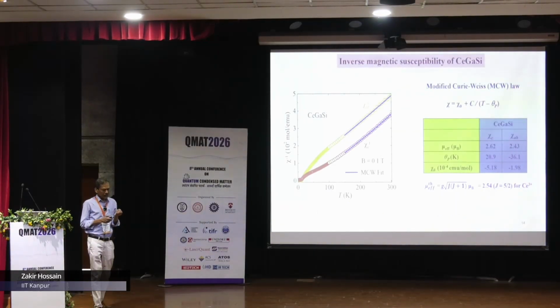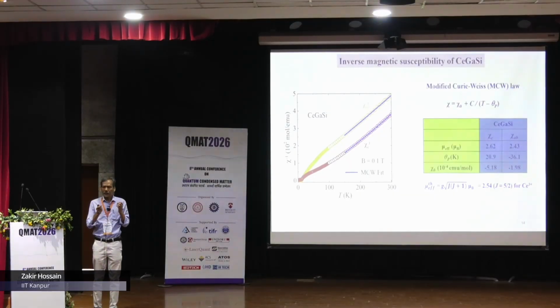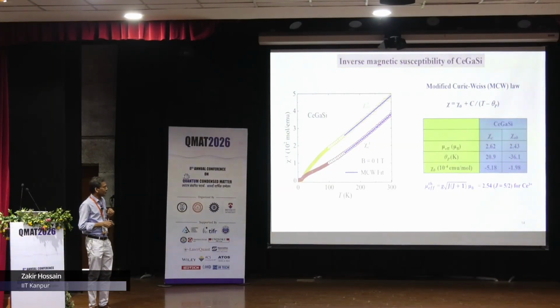We also, because of the cerium compounds, depending on the crystal structure and the environment of the cerium atom, the properties can be affected by the crystalline electric field. So in the lattice there are ions, and they can create some electric field, and that influences the properties of the crystal. So it determines in which direction, how much will be the magnetization, which direction will have more. So one can use these magnetic data or the heat capacity data to analyze the crystal field levels also.